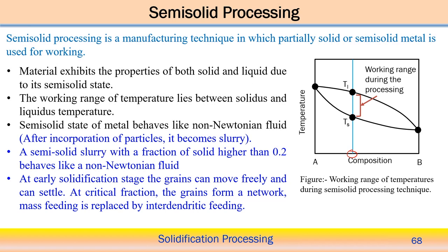So semi-solid processing is a manufacturing technique in which partially solid or semi-solid metal is used for working. In this case, the material exhibits both solid and liquid state properties because of its semi-solid nature. As already mentioned, the working temperature range is between the solidus and liquidus temperature for a particular material. But if we look at the semi-solid metal, it behaves like a non-Newtonian fluid. That means the relation between shear stress and velocity is non-linear. Once partial solidification occurs, we can treat it as particles, available with the remaining liquid, and that behaves like a slurry.